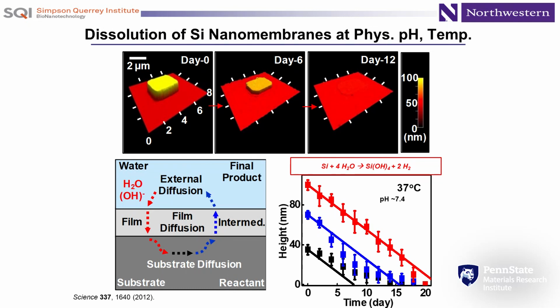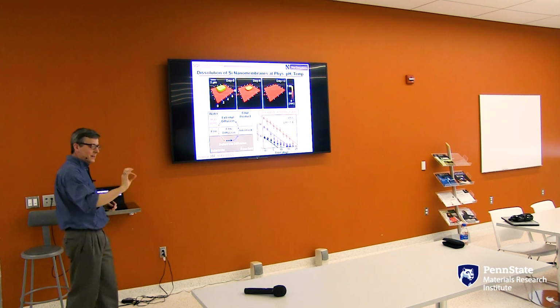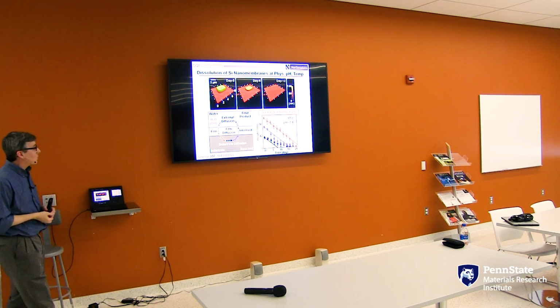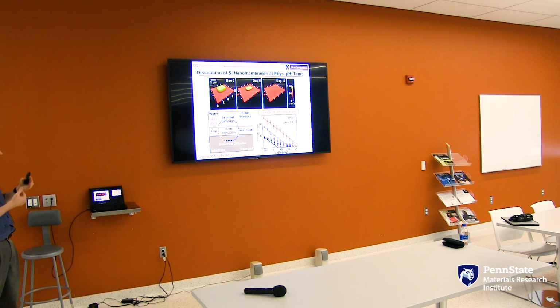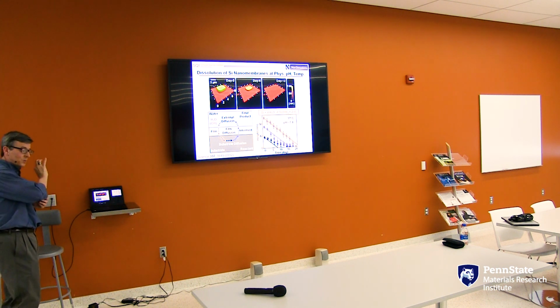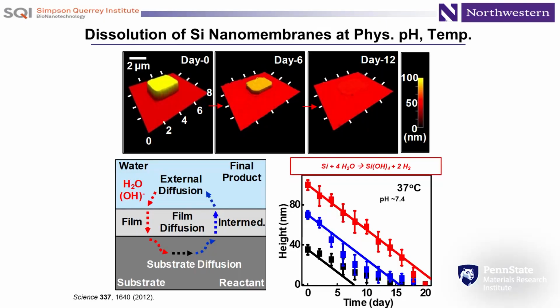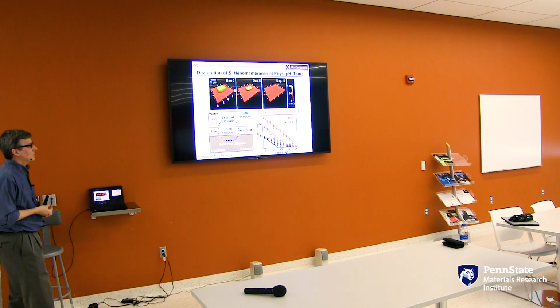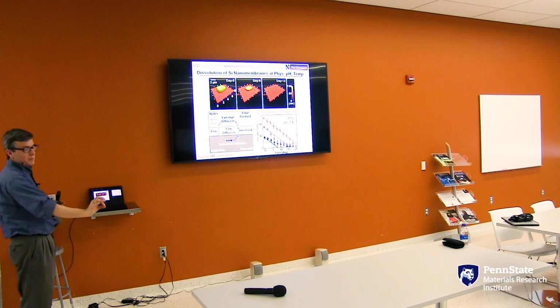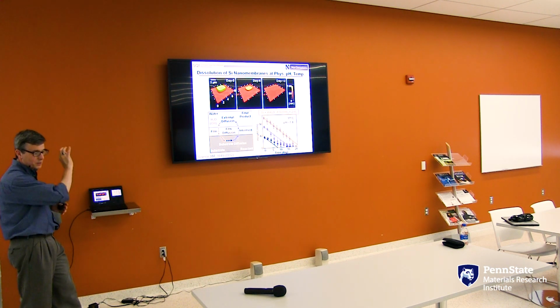But if you look very closely, it turns out that silicon does in fact react with water. It undergoes hydrolysis to form silicic acid and a little bit of hydrogen. But it undergoes that kind of hydrolysis reaction at exceptionally low rates, rates that would prevent observation of that kind of phenomena in a bulk piece of silicon. But if you're interested, as we were, in these very thin nanoribbons of silicon in your patient, you can take a piece of silicon with those kinds of geometries, place it in a phosphate buffered saline solution at physiological pH and temperature, and you can just watch it disappear at a rate of 1 to 5 nanometers per day.